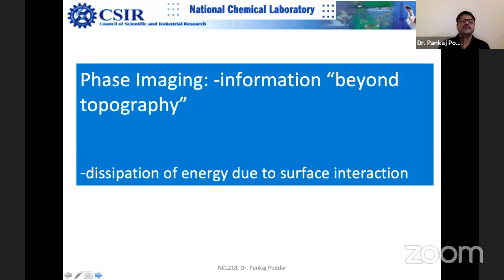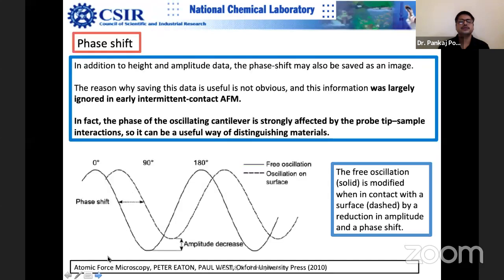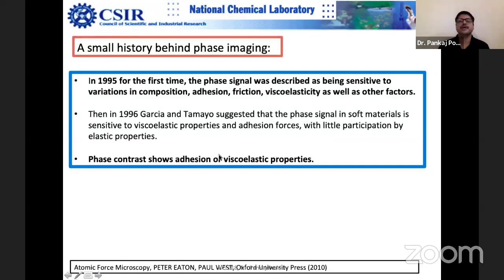So these are the things which you can read. Phase imaging is basically the dissipation of energy. Any phase change anywhere, whether it is your dielectric measurements, electrochemistry measurements with an impedance analyzer, magnetic measurements, or any optical measurement, wherever there is a change in the phase, that is because of the dissipation of energy. And dissipation of energy is due to the surface interaction, which depends upon the type of the surface. So essentially, phase shift carries the information about the viscoelastic properties as well as adhesive properties.